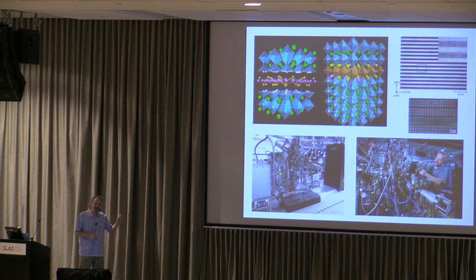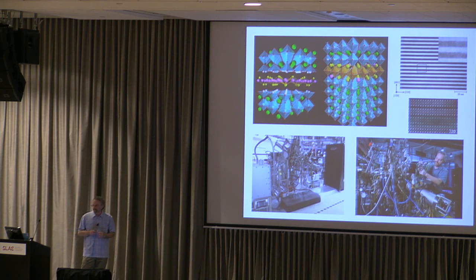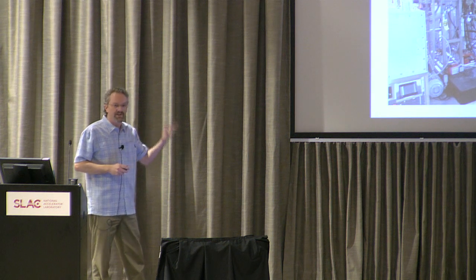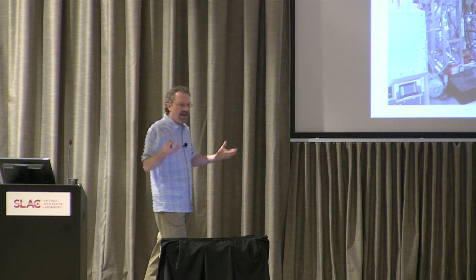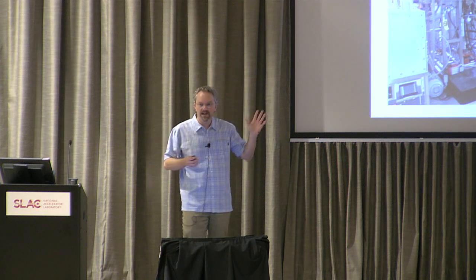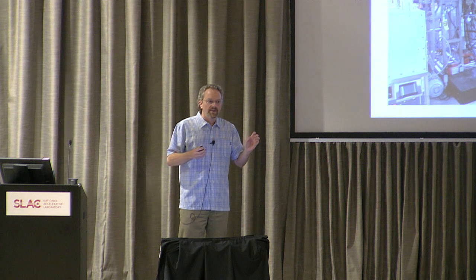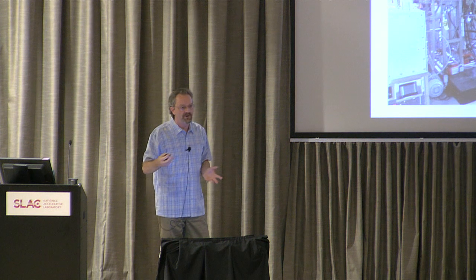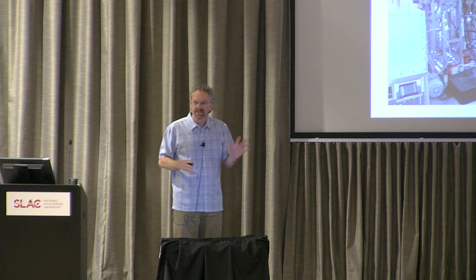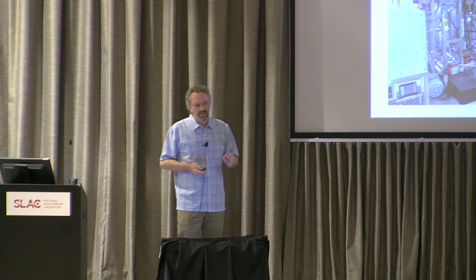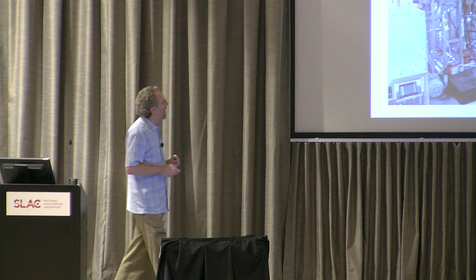One of the things we need to do is understand the electronic structure of these materials. But normally we can't directly look at the electronic structure of materials created by MBE — not because of a material problem, but because of the electron itself. When we try to look at the behavior of the electrons, if you take the material out into atmosphere, all the atmospheric contaminants — moisture, CO₂, CO, hydrocarbons — anything that sits on the surface may not affect the material, but it will destroy the signal we're trying to measure. So the trick is how do we get around that?